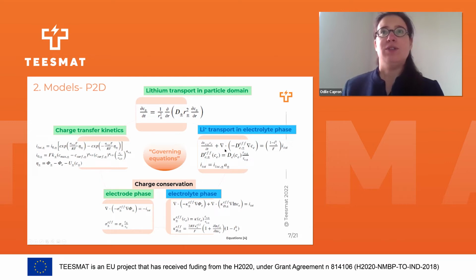And on the left side, you can see the lithium transport in the electrolyte phase. This equation applies to the electrolyte, which is part of the porous electrodes and also part of the separator, separating both electrodes, and through which the ions are moving from one electrode to the other. So you can see that these are complex equations. It's also to be considered always, as you see in the slide, the plus and the minus, because in fact all these equations are doubled, for both positive and negative. So when it comes to plus and minus, we have the same equation, one for the positive electrode and one for the negative electrode.